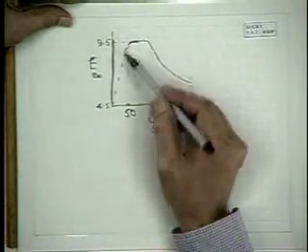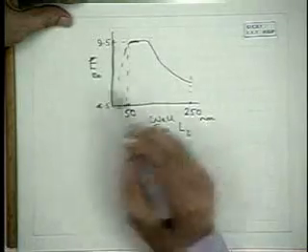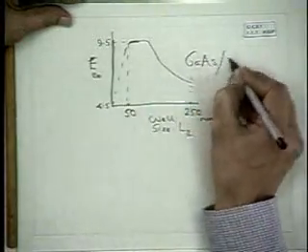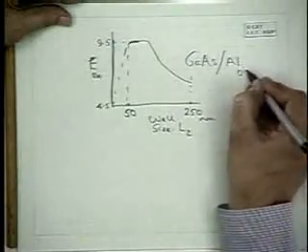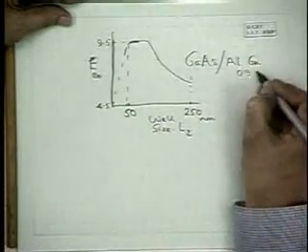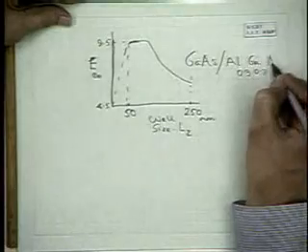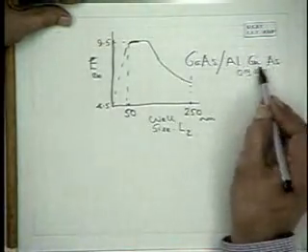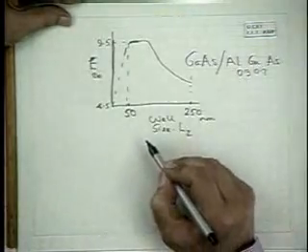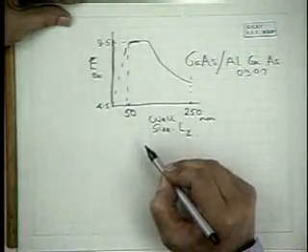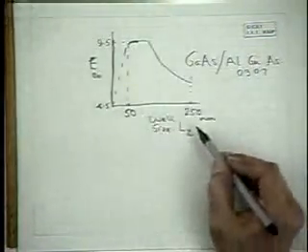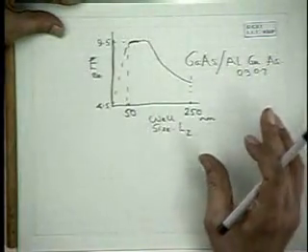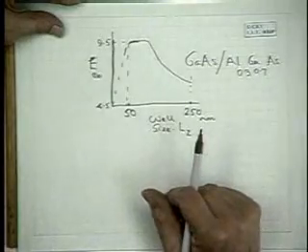This is particularly for a quantum well of gallium arsenide, aluminium 0.3, gallium 0.7 arsenide composition. This composition determines the height of the potential wells. So this explains why excitons are stable even at room temperature in quantum wells.